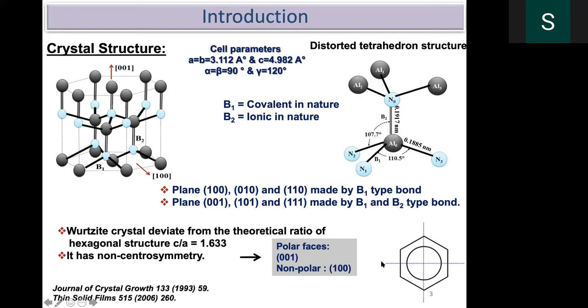So what is the benefit, if you ask? If it is non-centrosymmetric, it is basically an anisotropic material within a single crystal. So this can hold charges. That is something we are going to discuss in the later stages of this presentation. And since the basal plane is very strong, as I told you, the hardness will be very high compared to the C-axis orientation. That is what the already published journals show, and from that we can understand.